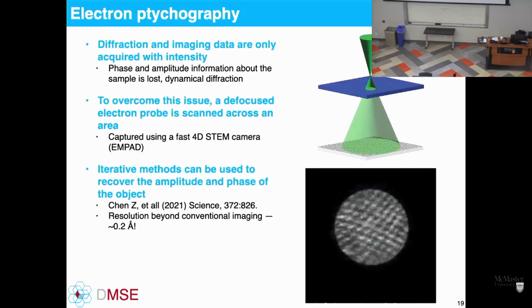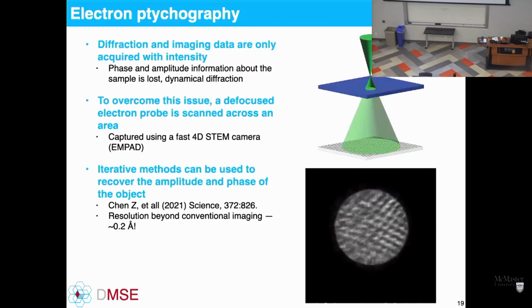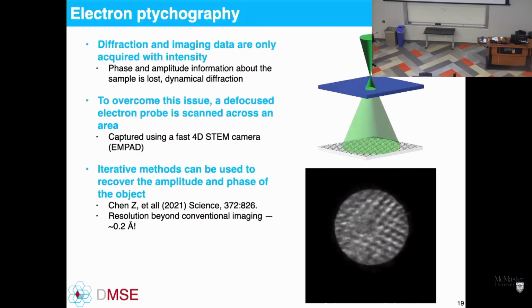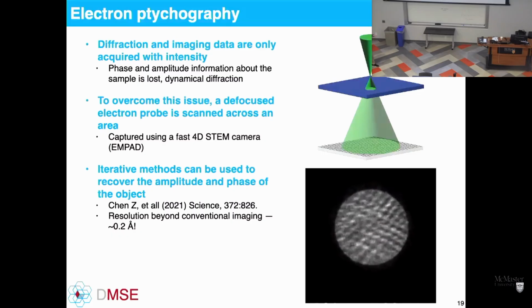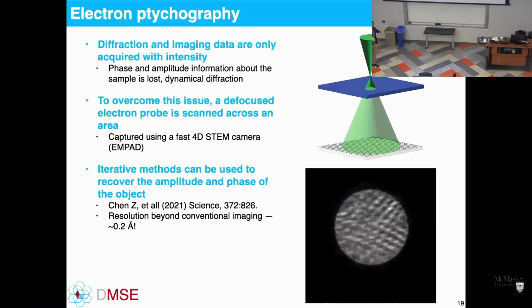So to overcome this issue, we use a defocused electron probe, and this is what ptychography is. We use a defocused electron probe. We scan that across our sample. We collect this with a high dynamic range detector, in our case an EMPAD, electron microscopy pixel array detector that was developed at Cornell. And by mapping that across, what you're seeing here is phase contrast information from the lattice being projected into that detector. I'm moving my probe across the sample and it's illuminating different regions. As that probe is scanned, it is tracking the same region. So that is the same atom, meaning that there's overlap between those probe positions as I'm scanning, right?